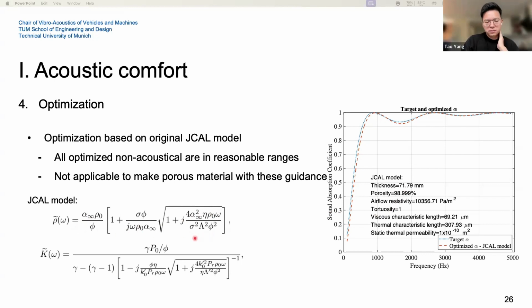I don't know if you're familiar with the JCAL model or not, but just to briefly introduce, this model is quite robust and it contains 7 parameters. In the optimization, we can get the thickness, porosity, airflow resistivity, tortuosity, viscous characteristic length, thermal characteristic length, and the last one is static thermal permeability. But okay, we got such long acoustic parameters. The point is, how can we produce the material with exactly the same parameters? In my opinion, it is impossible to prepare or produce exactly the same material with such parameters.